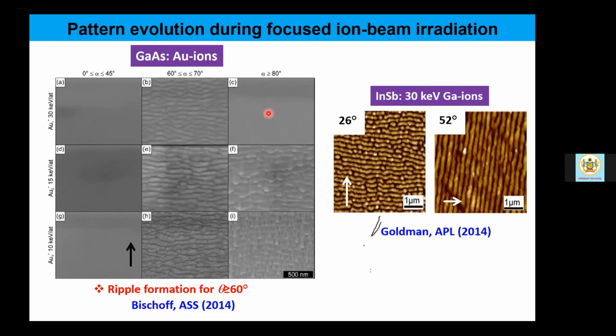And for incident angle greater than or equal to 80 degrees, the surface again became flat. For which condition? When gold energy was 30 keV per atom. For 15 keV per atom, this is the situation. Even at 80 degrees or more, there were ripple patterns. But for 10 keV per atom, one gets to see pattern formation again at incident angles higher than 80 degrees. So, very varied kinds of pattern formation are reported.